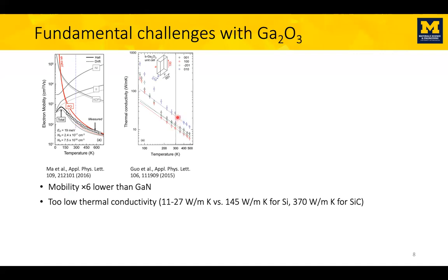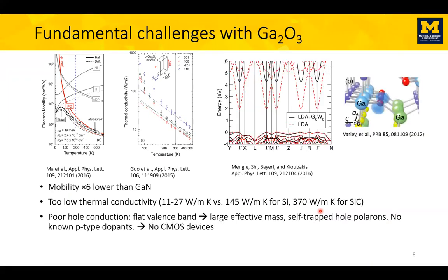It's anisotropic because it's an anisotropic crystal structure, but the values are in the range of 10 to 30. Again, these are at least one order of magnitude lower than competing technologies such as silicon carbide or silicon. So you produce more heat, it's hard to extract this heat, so these devices heat a lot, and that degrades the performance a lot.